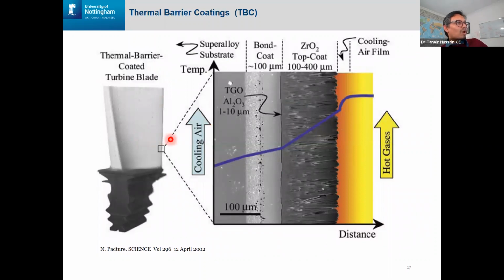The reason it became so popular is that in the conventional engine, the one I'm holding at the moment, this is the state of the art. We have a bond coat. On top of that bond coat, we have a thermally grown oxide, or TGO, which is an alumina. Then on top of that, we have a bird's feather-like columnar structure called EB-PVD coated thermal barrier coating. And EB-PVD, this bird's feather-like coating, is quite desirable. That means at high temperature, they can expand, and when the engine is cooling down, they can contract. So essentially, they are highly strain tolerant.